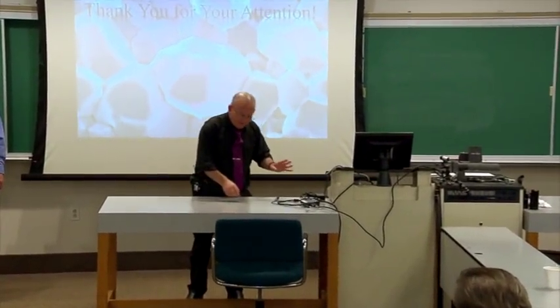Absolutely. Thank you. Peter? So in these field-assisted experiments, your bulk densification and grain growth, what's the effect of the field itself? Is it sort of like an onset, or is it linear behavior, or is it a maximum field that you need? I don't know. In SPS, and in flash, which is a much better, more controlled experiment, there is an onset voltage for magnesia doped alumina in order to start this flash. What do you mean voltage?